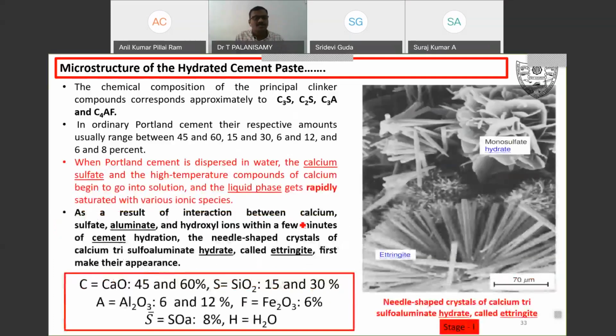Then the microstructure of the hydrated cement paste. I come to the exact picture today. The chemical composition of the principal clinker compounds corresponds approximately to C3S, C2S, C3A, and C4AF. In ordinary Portland cement, the respective amounts usually range between 45 to 60, 15 to 30, 6 to 12, and 6 to 8 percent.